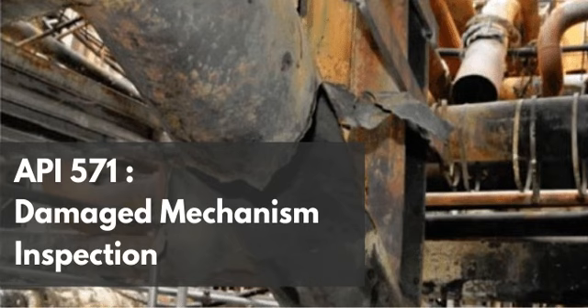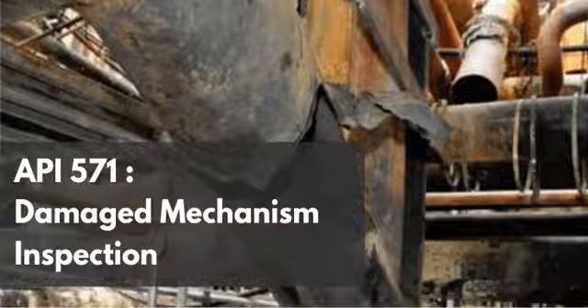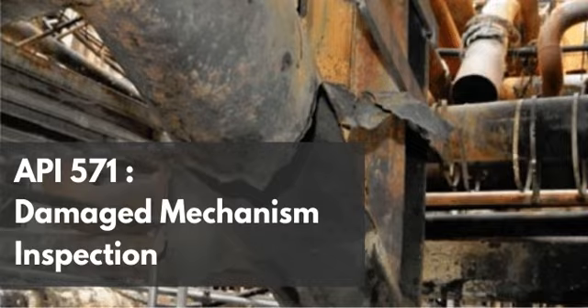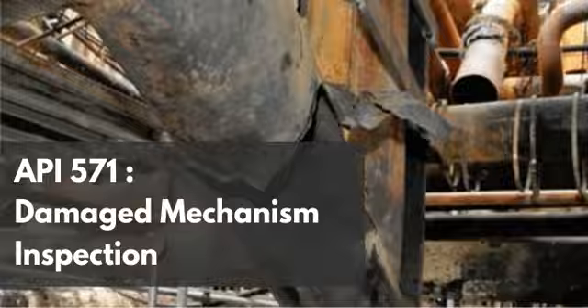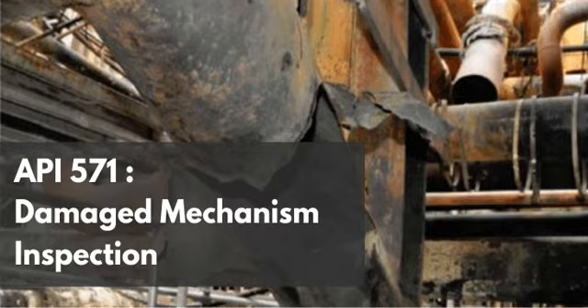Precisely. To know the true remaining strength of the tube, you have to physically extract a sample. You have to cut a piece of the tube out, take it to a lab, polish it to a mirror finish, etch the surface with highly specific acids, and look at it under a high-powered metallurgical microscope. That sounds intense. It is. Because only then, under massive magnification, can you actually see the dark, jagged network of brittle carbides penetrating through the grain boundaries of the wall thickness.